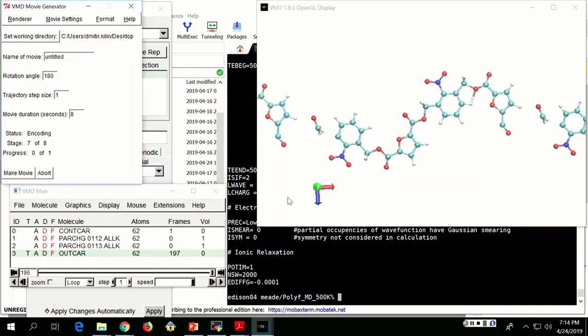Well, you can look further for practical applications like solar cell or cancer therapy, but the technical goal is to facilitate hole transfer. If you excite both electron and hole in the quantum dot, as time passes by, it transfers positive charge onto the dye. And this is LUMO, right? Yeah. So LUMO stays on the quantum dot, and this is a very small percent, and the hole is on the dye. Very good. Very interesting.